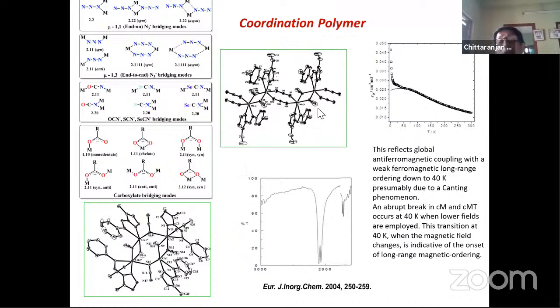And this number of unpaired electrons, if they join in the process of the magnetic moment, it is observed, as you see, that with changing temperature, magnetic moment increases, and after a certain temperature, its magnetic moment is enormously increased. That is, a ferromagnetic behavior is observed at low temperature. This is because of the structure of the molecule. And this structure leads to the remnant magnetism.